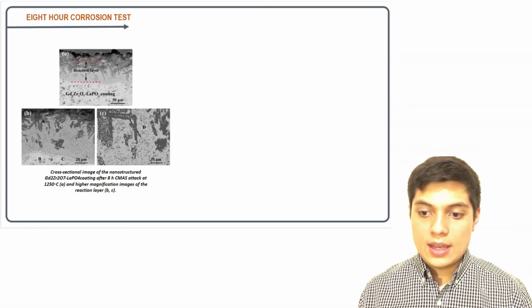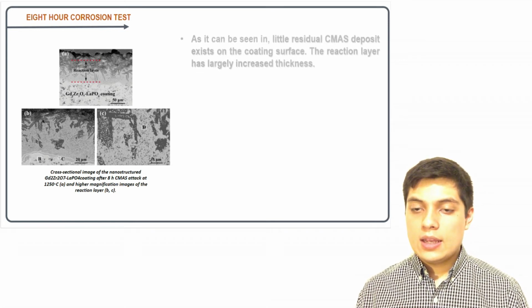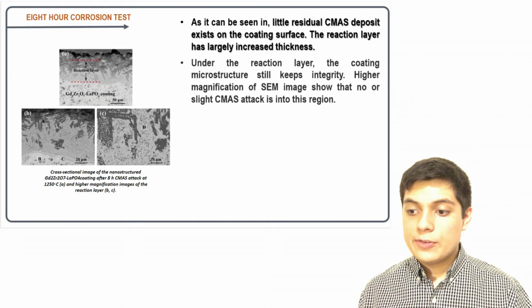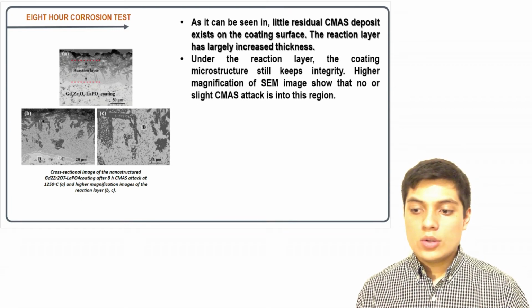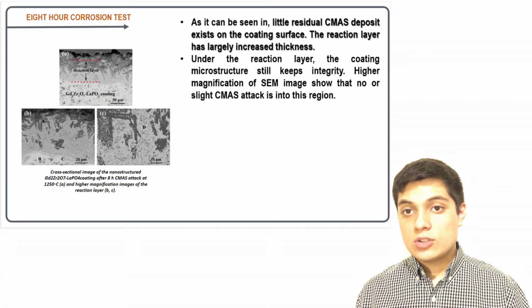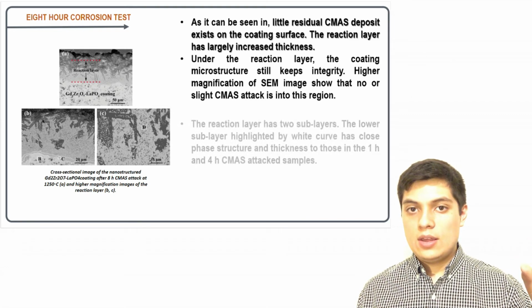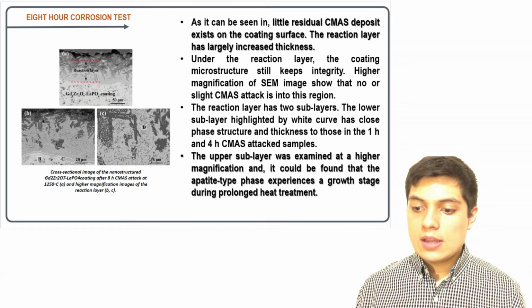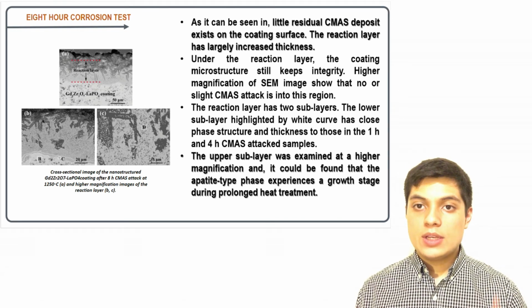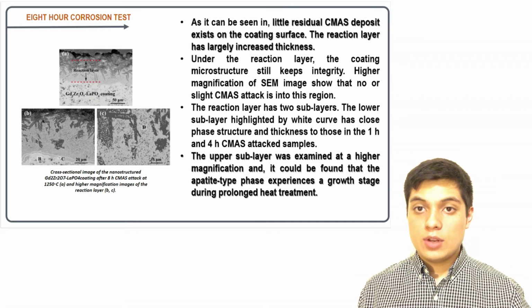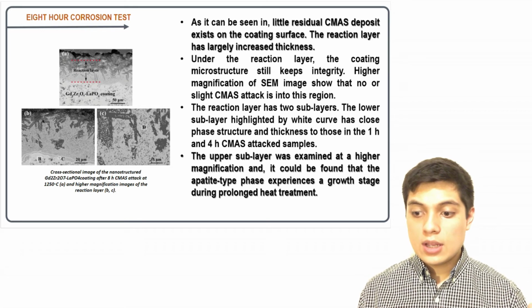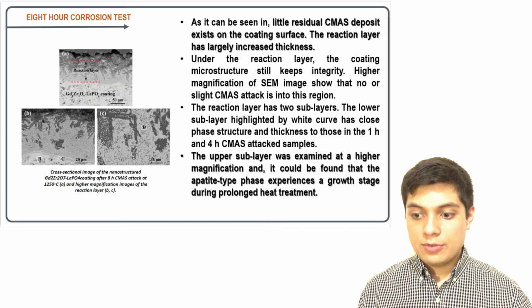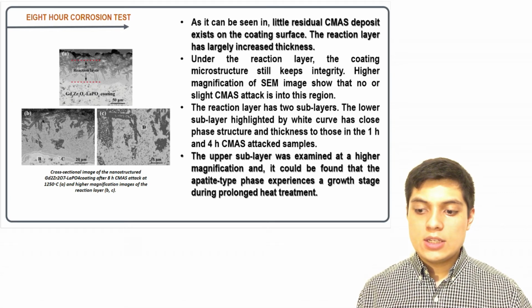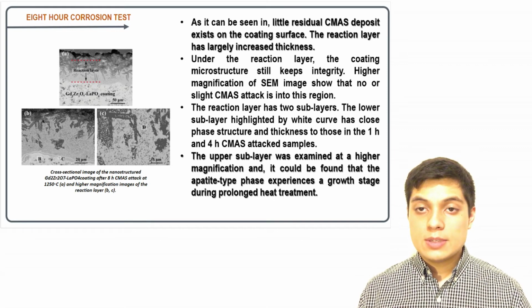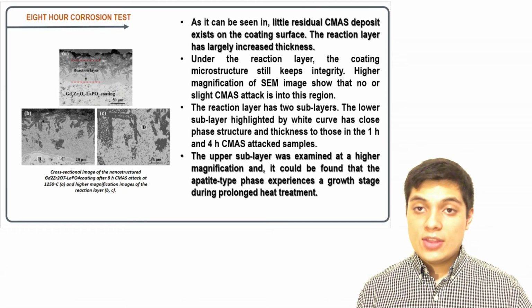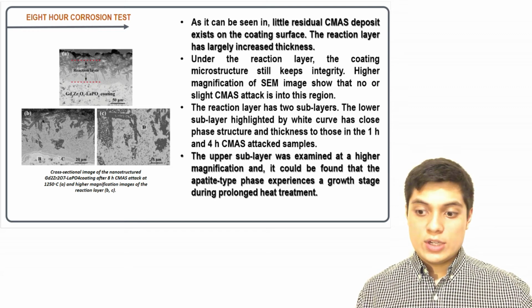And finally, we have the 8-hour corrosion test, and it is important to say that there was little residual CMAS deposit on the coating surface, and the reaction layer has increased its thickness. It is also important to say that from these 2 sublayers, the upper sublayer was examined at higher magnification, and it could be found that the apatite type phase experiences a growth stage during prolonged heat treatment. So this means that when you increase the heat treatment time, the thickness of the upper sublayer increases.